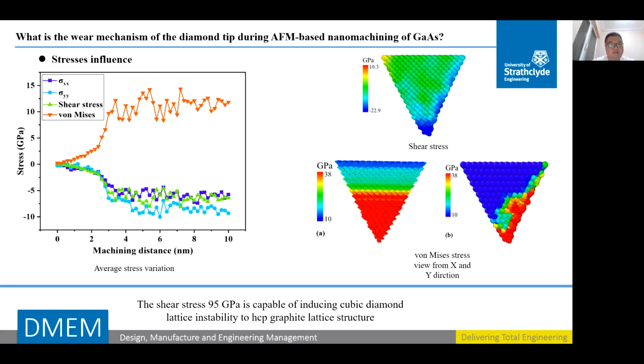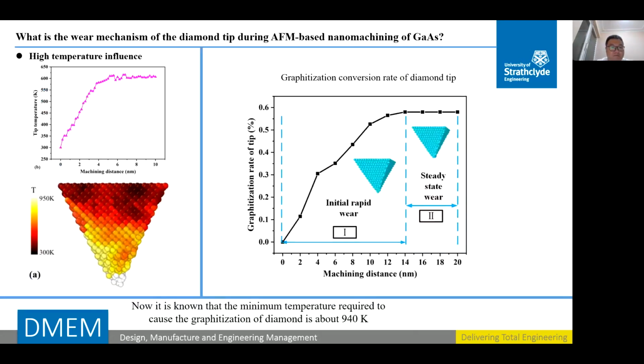This indicates that besides shear, some other factors can also cause graphitization of the diamond tip during nanometric cutting of single crystal gallium arsenide. On this page, we can see the average temperature of the diamond tip dramatically increased at the start of nanometric cutting. And then the average temperature kept steady at around 600 Kelvin. Another observation from this figure was the highest temperature, around 950 Kelvin, which was concentrated at the apex of the diamond tip, which was also the incipient place of graphitization.